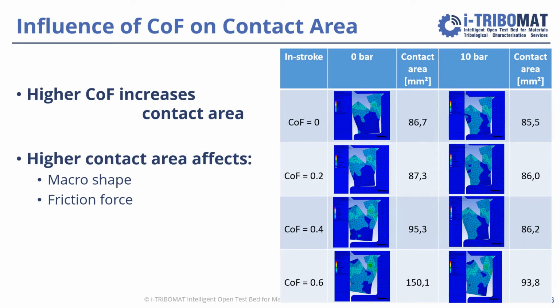So let's look at the influence of the coefficient of friction on the contact area first. As you can see here on those cross sections for the 0 bar chamber pressure, when you increase the coefficient of friction, the contact area increases gradually. And at the end, the increase is rather steep. The same applies for another chamber pressure. Here, an example for 10 bar is shown. The contact area again increases, just to other values. So whatever the operating conditions are, the qualitative information is the same. Higher coefficient of friction increases the contact area.